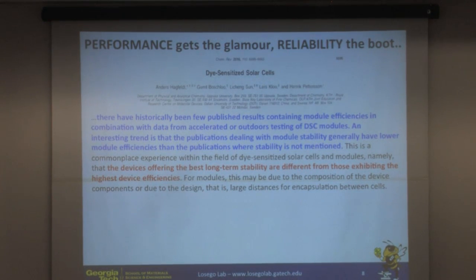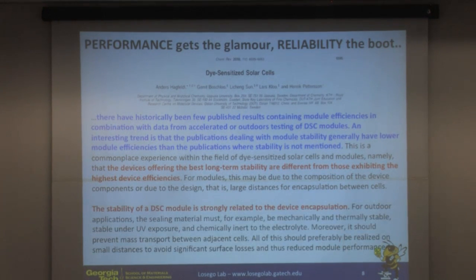In this review, they say there have historically been few published results containing module efficiencies in combination with data from accelerated or outdoor testing of DSC modules. An interesting trend is that the publications dealing with module stability generally have lower module efficiencies than publications where stability is not mentioned. So people often just report performance and not reliability. In fact, they go on to say that the devices offering the best long-term stability are often different from those exhibiting the highest device efficiencies.